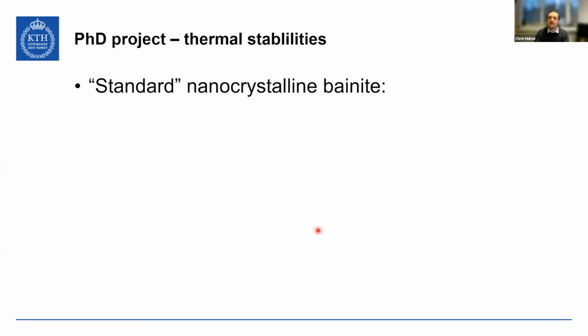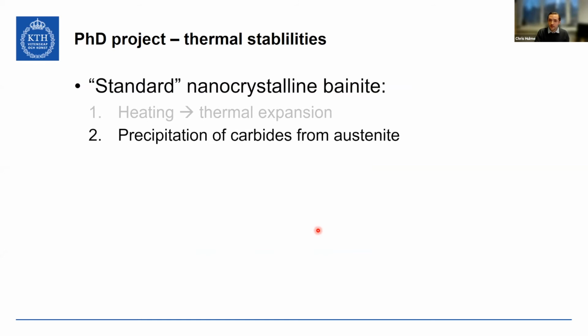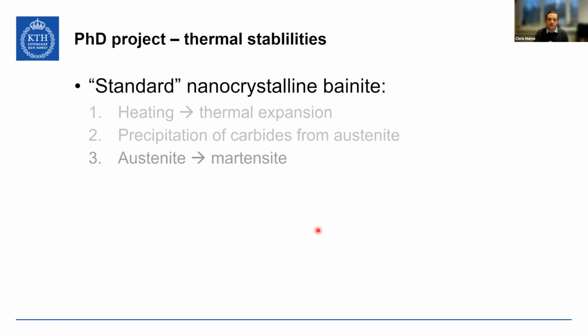So it was known before I started that if you have nanocrystalline bainite or superbainite and you temper it, initially you just get thermal expansion until eventually you precipitate carbides from the austenite, at which point the austenite lattice parameter and the dimensions of the sample contract due to the loss of carbon from the matrix. This has been published by Thomas Sourmail with dilatometry, and you can see it very clearly in some of the X-ray synchrotron results that I'll show you soon. Upon cooling, the metastable austenite transforms to martensite, and of course that makes the whole structure weak, brittle, and therefore weak under tension.